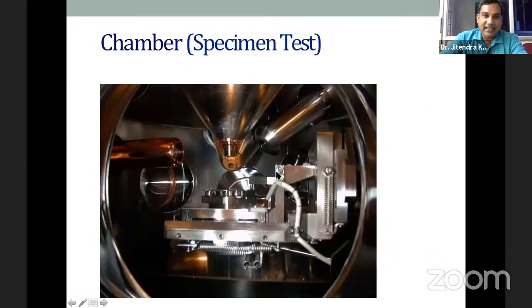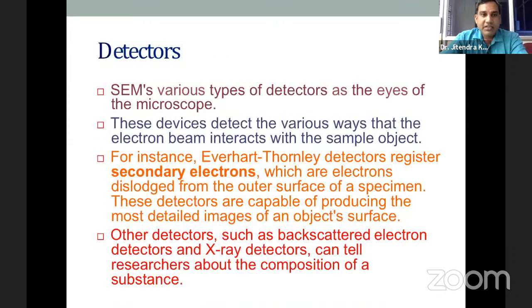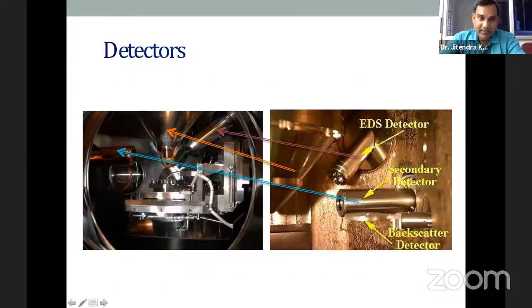This is a close view of your specimen chamber, where you can hold your specimen. From the top, the high intensity electron beam falls over the sample, and these are the detectors. This is called a secondary electron detector, which detects the secondary electrons emitted over the surface and captures the surface. This detector plays a very important role. It was developed by Everhart and Thornley, and that's why it is known as the Everhart-Thornley detector. It considers secondary electrons only, and other electrons like backscattered, X-ray and Auger are suppressed by some other suppressor. These are the segments you can see here.